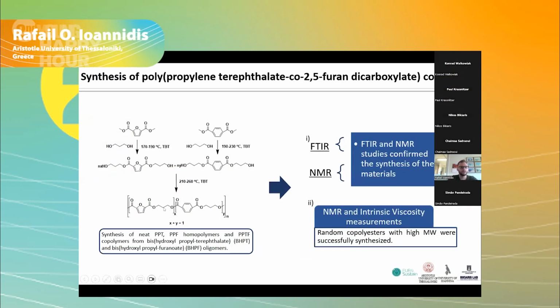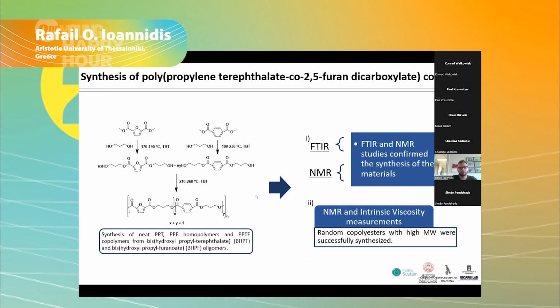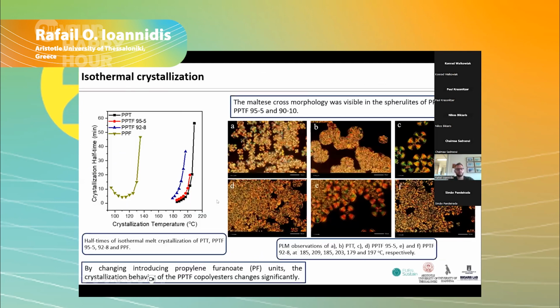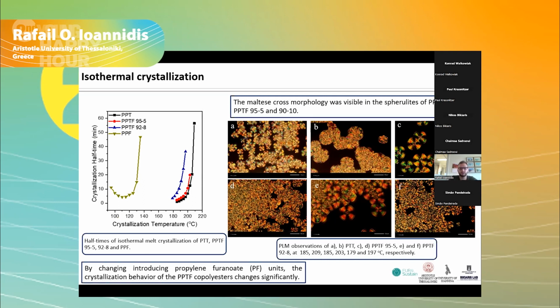The objective of copolymerization is exactly to combine the advantage of each polymer, the high crystallization rate of PPT, and the bio-based nature and the exceptional gas barrier properties of PPF. Because of the presence of the furan ring, this causes a rigidity of the system and enhances rigidity, and we observe that during isothermal crystallization kinetics, the crystallization rate of the copolymers was decreased concerning the crystallization rate of PPT. Also, you can see here a nice observation of PLM, and it's clearly visible the Maltese cross morphology of the 95-5 and 92-8 compositions of the copolymers.